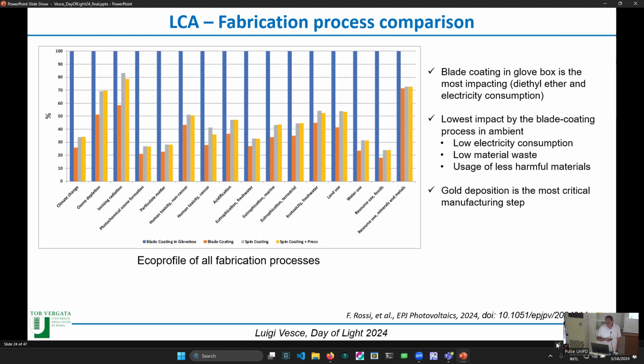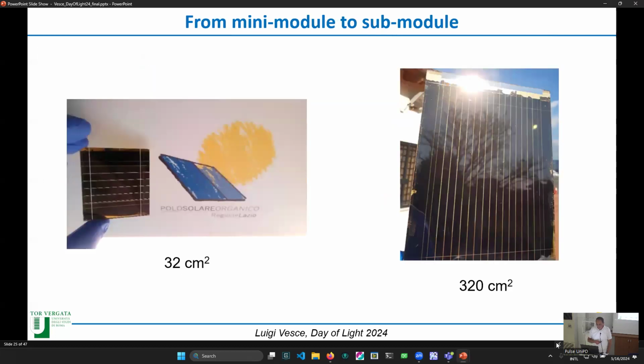The lowest impact, as we expect, is by blade coating. This is because you have low electricity consumption, low material waste, and also use less harmful materials. It is not in this graph because this is an accumulated graph, but the gold deposition is the most critical manufacturing step, because you have to use gold, and you have to use a high vacuum process by evaporation. Then at the end we will see how we can remove the gold. But we want to further upscale.